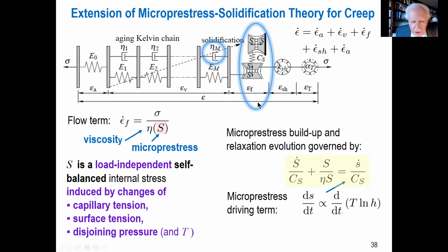That can be modeled by recognizing that the structure is upset, or by internal stresses. These can obviously be enormous in disjoining pressures in hindered adsorbed layers. And this S is called micro-prestress, or if you prefer, you can call it eigenstress, same thing. There is basically a relaxation equation, so we speak of relaxation of micro-prestress. And the interesting point is, micro-prestress is built up at the beginning, then relaxes, but when there is a change of moisture content, it increases micro-prestress.